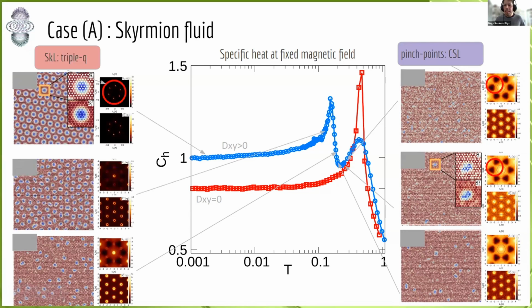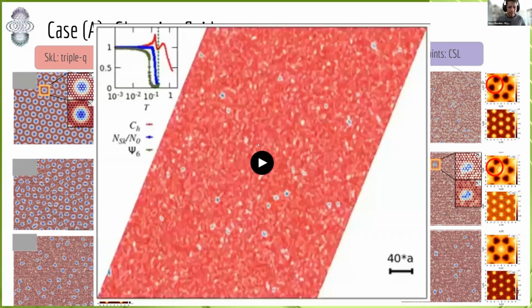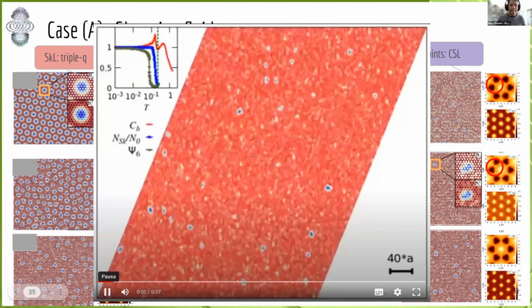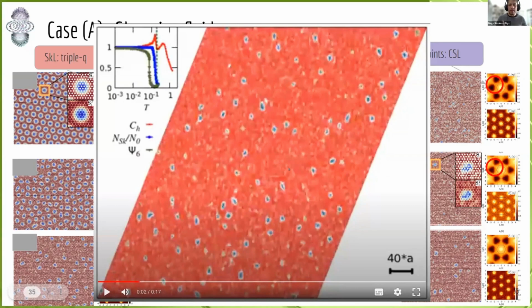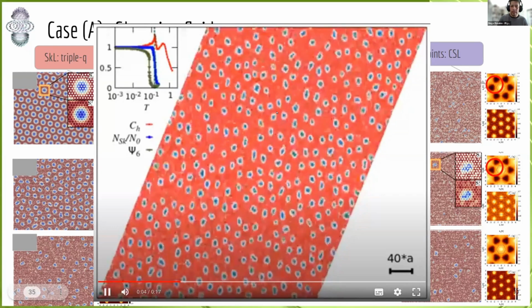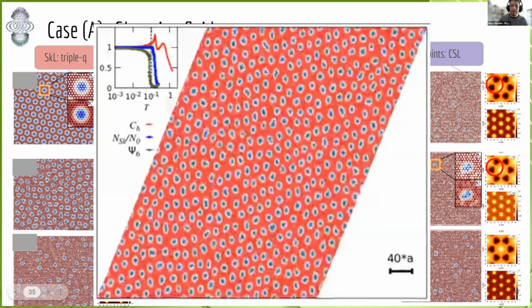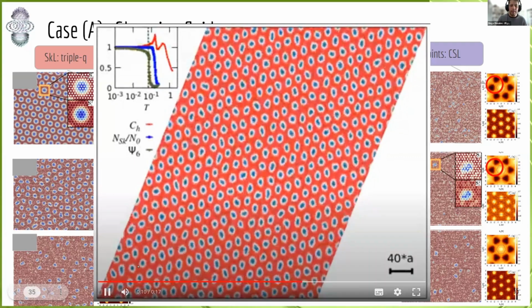We start in some kind of gaseous skyrmion state at this point, and we finish in the skyrmion crystal at low temperature. So let me show you a video of this evolution, starting at this point with a very small number of skyrmions, and we finish at this point in the skyrmion crystal. The difference, if you remember the previous video, is that now we have well-defined skyrmions, and the number is not too large. It's a very small number of skyrmions. And now we have a skyrmion crystal, all solid. Okay, this is the difference.